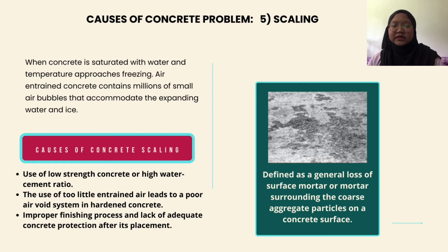There are a few causes of scaling. First, the use of low strength concrete or a high water cement ratio. Then the use of little entrained air leads to a poor air void system in the hardened concrete. And then an improper finishing process and lack of adequate concrete protection after its placement.